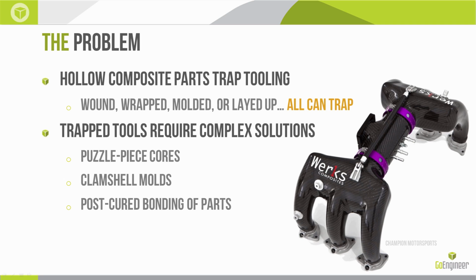How do you deal with that trapped pattern? Typically, how it's been done is you create a core made from really puzzle pieces, separate pieces of the core that can come out separate from each other. So you might have an internal part that's removed, and then the outer walls can then be moved and removed. Or you deal with a clamshell mold. And if you do a clamshell, then your parts typically have to be bonded after they're cured.